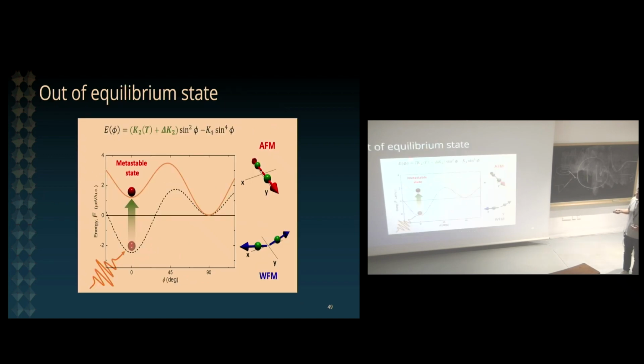So this is telling us that we are really creating an out of equilibrium state with a reconfigured magnetic potential. What I'm showing here is the result of our analysis of all these frequencies versus time, which allows us to reconstruct the shape of the potential at equilibrium and out of equilibrium. And what you can see is very interesting. At equilibrium, your ground state here is, let's say, in an energy state that is well below the energy of the competing state. However, when we excite the system, we bring it out of equilibrium, and the system is suddenly in a metastable state. In principle, there is another competing minimum here where the system could flip.